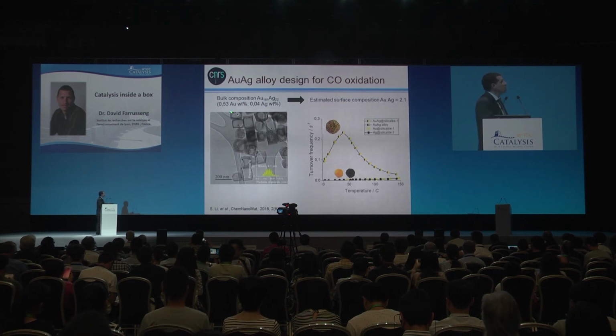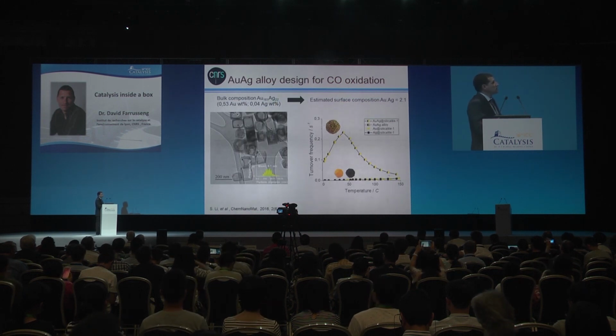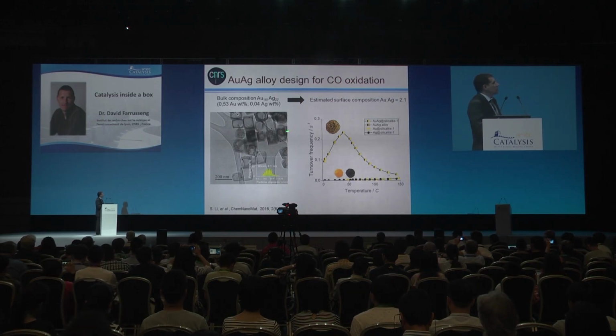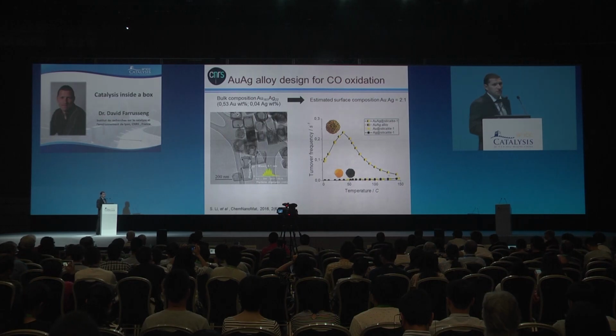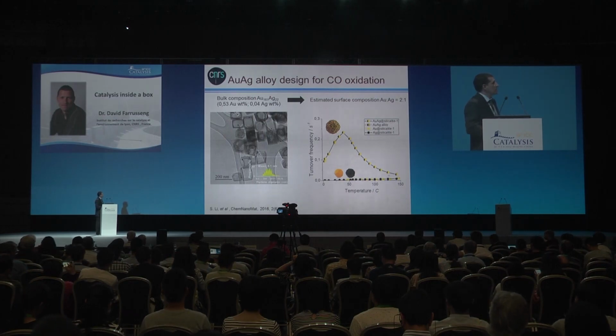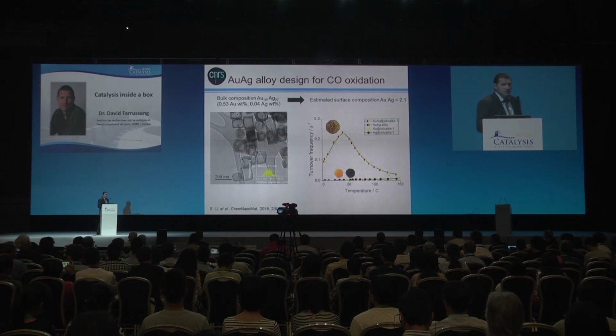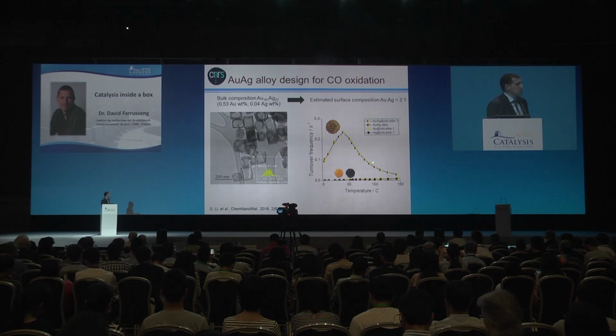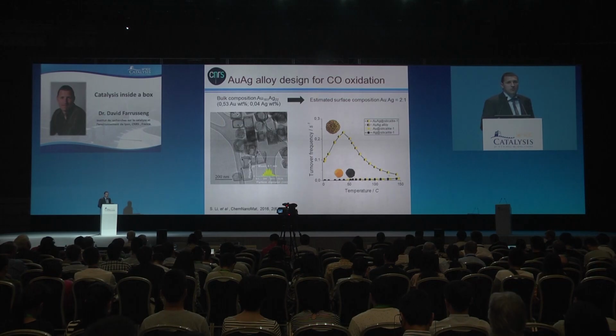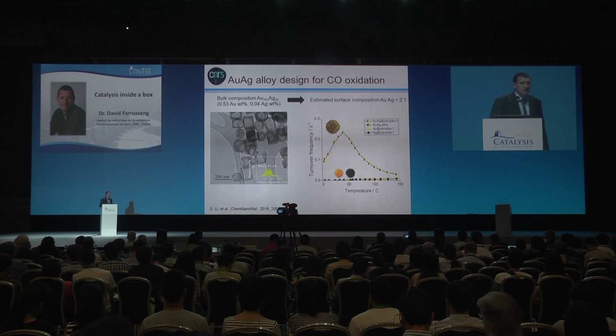So we did it here. We prepared gold-silver nanoparticles encapsulated in silicalite-1. Again, every cavity is filled by one nanoparticle of 8 nanometers. And then we tested that in CO oxidation. We tested first the pure components, the gold and the silver, and you see here both are not active, as I said earlier. But the mixture, the alloy, is, and actually this is a fingerprint that at the surface we have both metals.